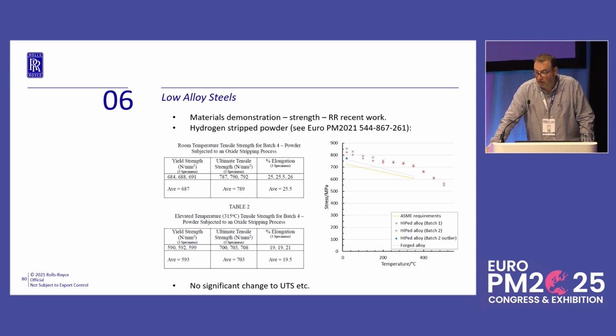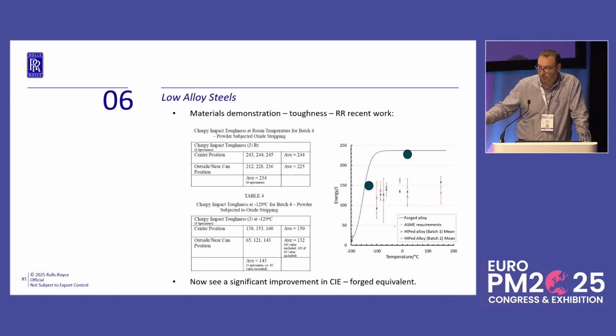And again, what we find is it doesn't really hurt the tensiles at all. There's a very small improvement in the elongation and the reduction in area, but they were generally fine anyway. So good, but nothing of concern there. Certainly nothing detrimental. On the toughness, however, the Charpy is chalk and cheese. By really managing to get rid of the oxygen, suddenly we've now got powder HIP material that we can say is the equivalent of the forging route. And that really is where we want to be.